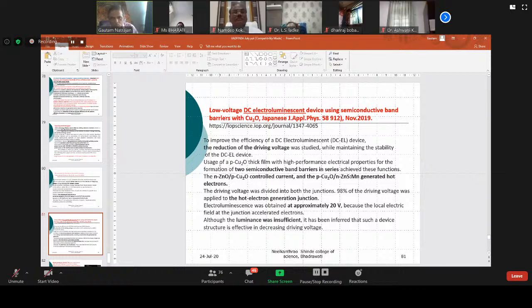Driving voltage was reduced using P copper oxide thick film with high performance electrical properties for the formation of 2 semiconductive band barriers in series. It was achieved. N zinc oxide, P copper oxide, controlled current. And p-Cu2O/n-ZnS:Mn generated hot electrons. Hot electron means high energy field electrons. And high field, whatever high energy electrons are generated, they are hot electrons. Then driving voltage was divided. 98% was applied to hot electron generation. The electroluminescence obtained in 20 volt. That is most important. 20 volt. Okay. Luminescence was insufficient. Means still more work has to be done. That is the report. Okay.